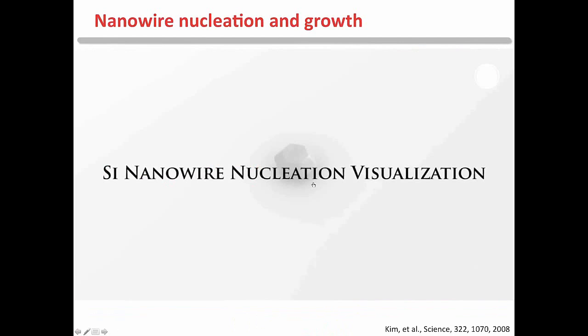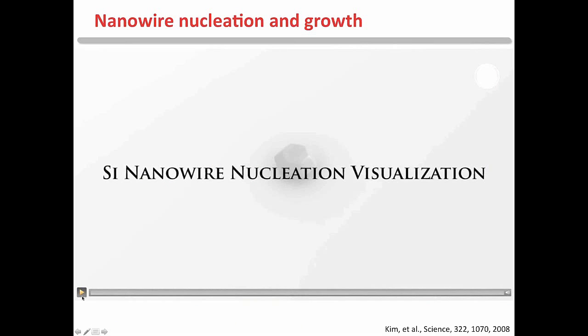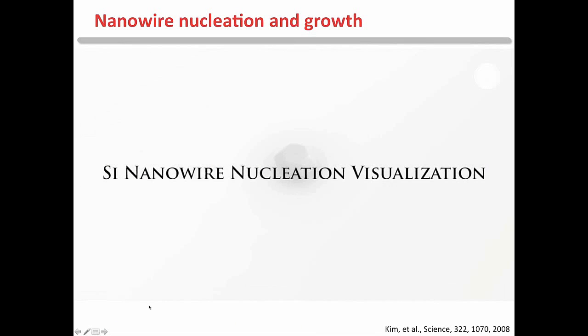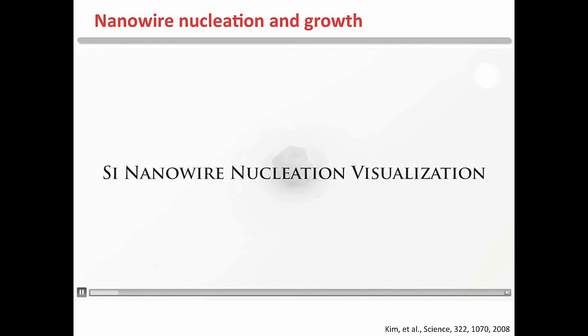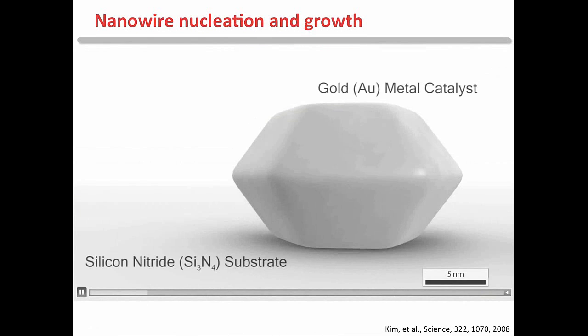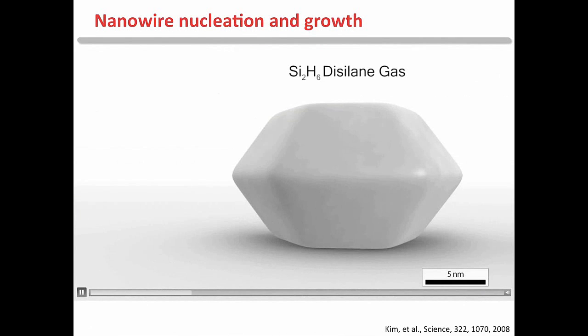So a while ago, we had a paper where we were looking at the nucleation process, and as part of this, we made a fun little movie to show this in a little bit more detail. And so here again, you start off with a solid gold catalyst. In this case, we were looking on a silicon nitride substrate, so they did not grow oriented, but rather kind of crawled along the substrate.